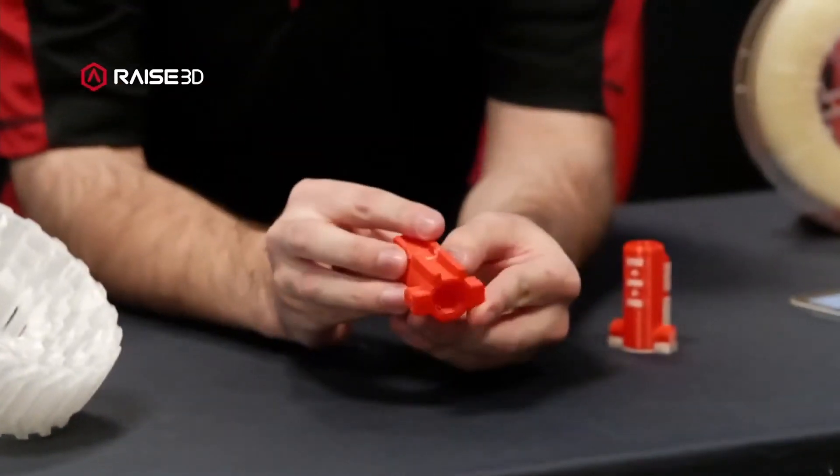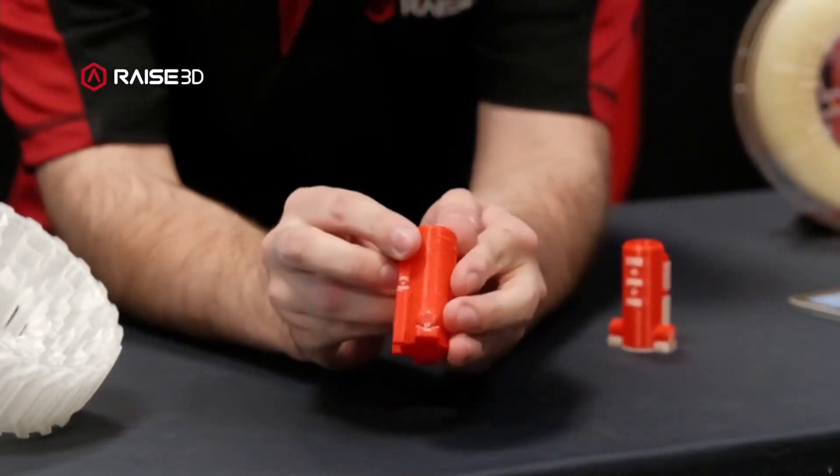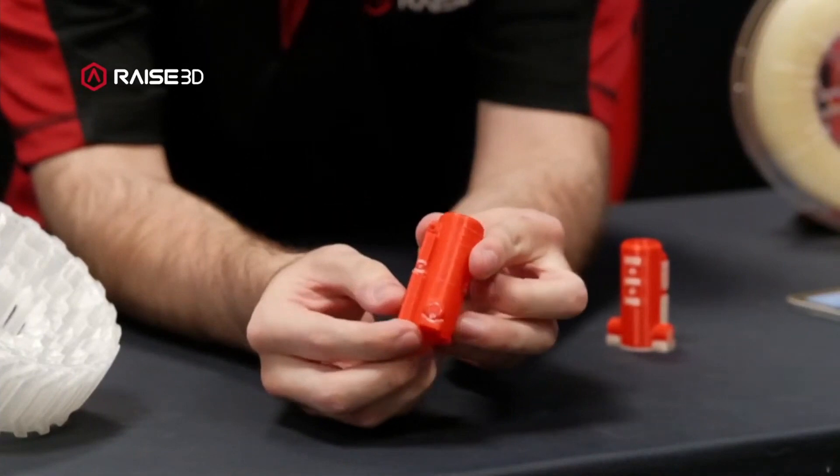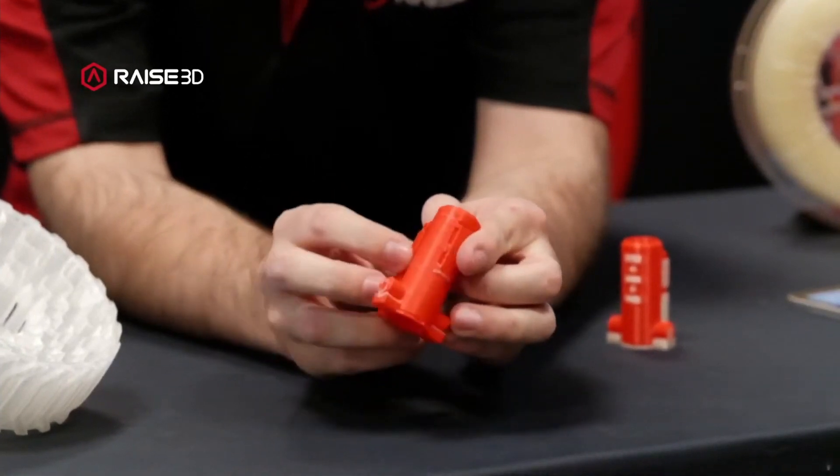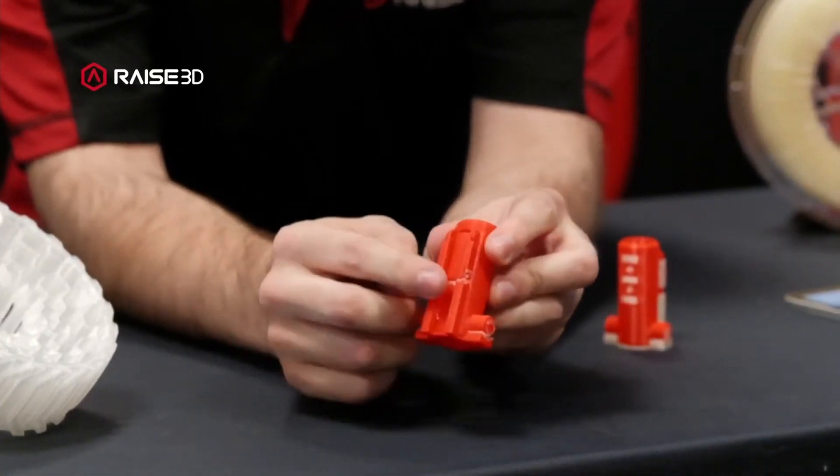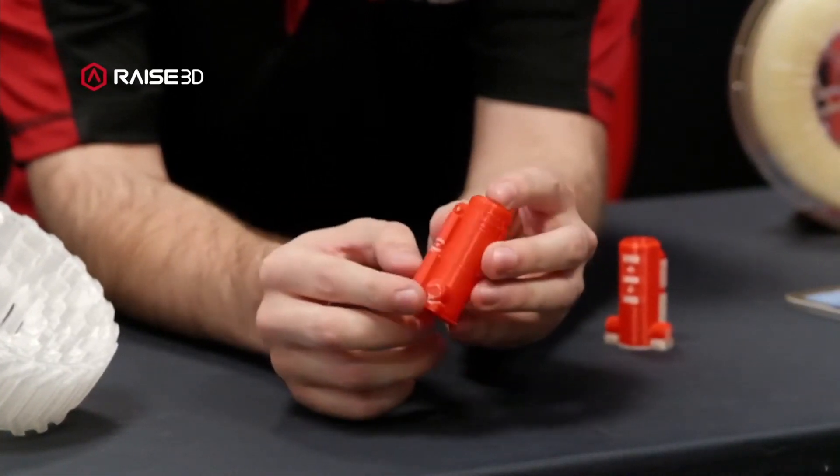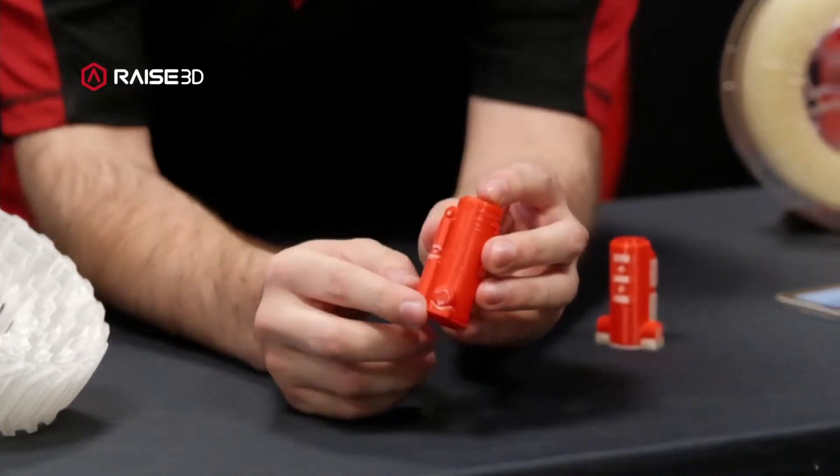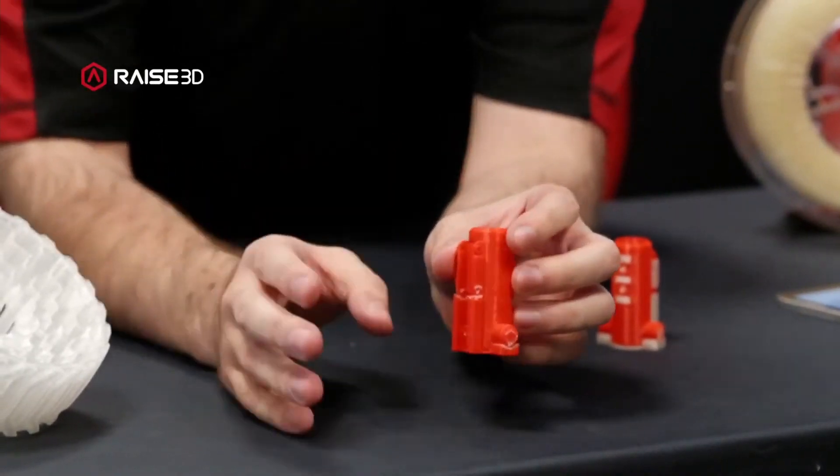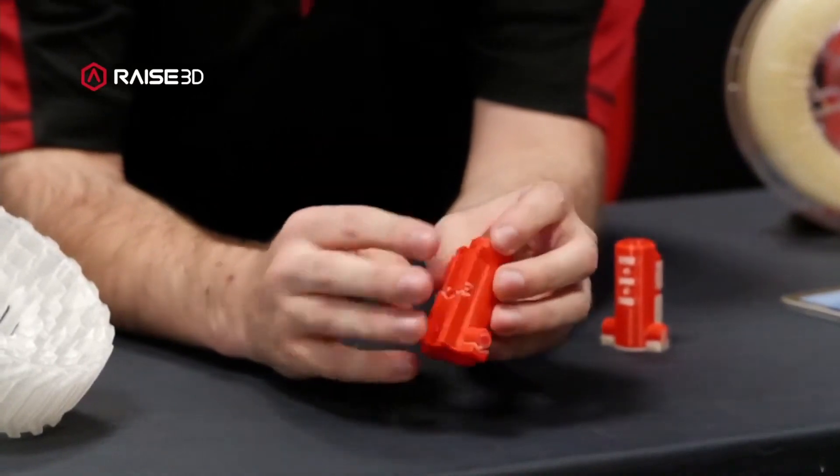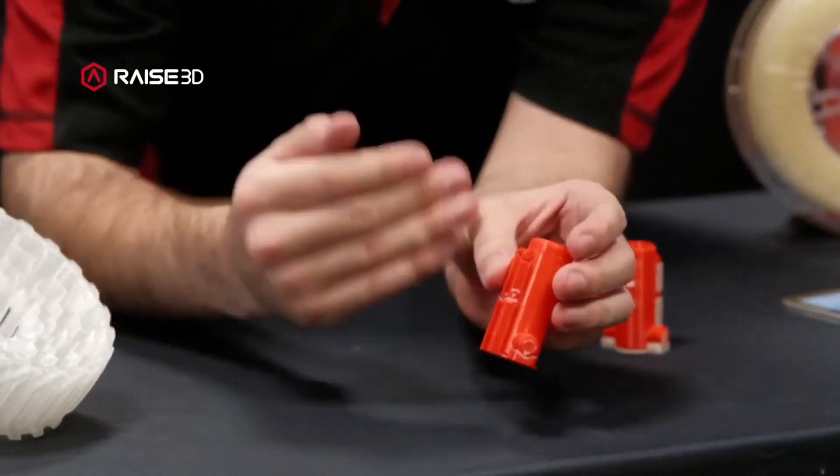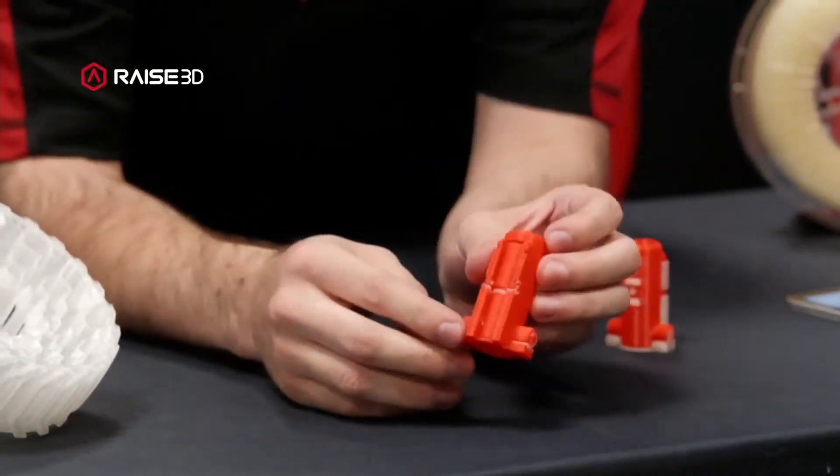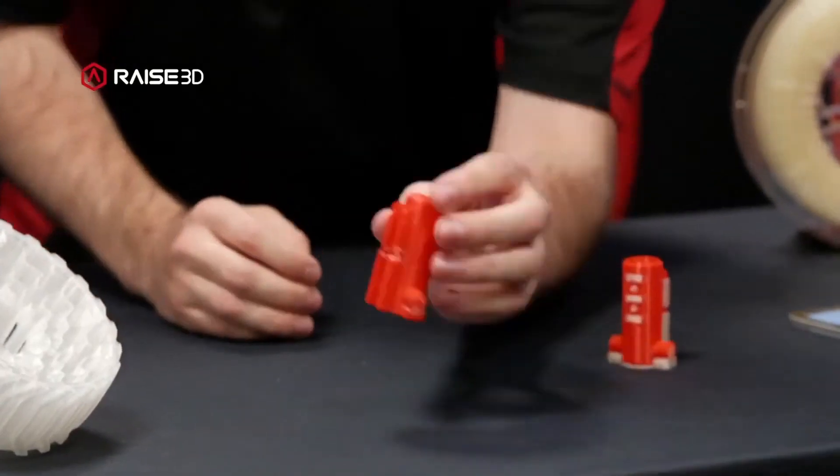It works really well for other things like running interface layers on parts. So you can get in there, I have this part changed, that way it's running most of the support structures out of PLA material and then just capping off those supports with PVA. So when I dissolve that out, it saves on the more expensive PVA material, but I can still get really good quality prints with those interface layers.